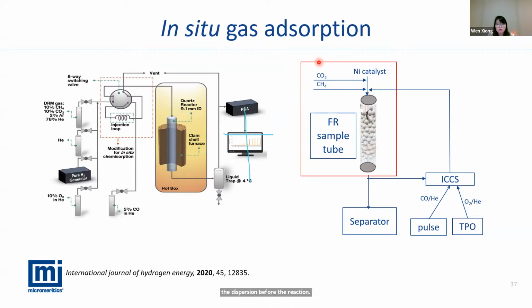And then thirdly, we flow the CO2 and the methane to the catalyst, recording the production from the sample tube as a function of time, or temperature, or pressure, whatever you want, to check the dry reforming performance of the nickel catalyst. We can go to the separator to separate the products, for example the water or methane from the reaction, or other products, whatever you want. And then we do the online recording by either MS or GC to record the reaction product.